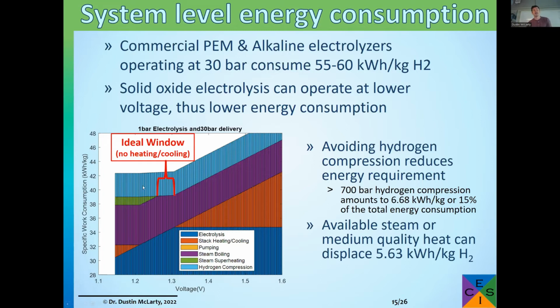And then above that, if we were operating at atmospheric pressure, we would have to pay for the energy of compressing that hydrogen, that's shown in the blue. And just as a relative measure of how significant that hydrogen compression work is: when you go all the way up to 700 bar, which is delivery pressure for vehicles, this 2.5 kilowatt hours per kilogram for hydrogen compression actually increases all the way to almost 7. So it's about 15% of the total.